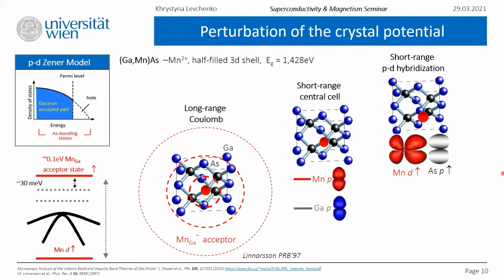Because the impurities are closer and long-range Coulomb potentials are screened, this leads to an imperfect metal with disorder-broadened and shifted bands. Impurity and host bands are merged into one inseparable band, whose tail may contain localized states depending on the concentration and disorder. So just like in other doped semiconductors, if the Mott criterion is fulfilled, that is, if the average distance between holes becomes smaller than 2.5 acceptor radii, the Anderson-Mott insulator-to-metal transition occurs. The fact that the holes cease to be bound to the manganese ions is seen in charge transport, magnetic circular dichroism, and electron paramagnetic resonance.